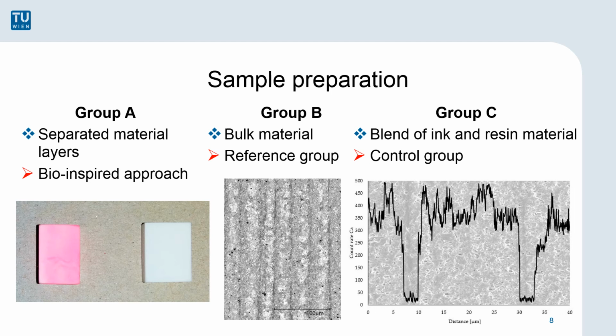To ensure that a potential effect is related to the structure of the samples with separated material layers and not from the addition of a soft material, a third group is produced. This group consists of a blend of resin and ink mixed before the printing process. These samples are printed solely with the SLA process. The amount and the ratio of ink and resin for groups A and C are identical.